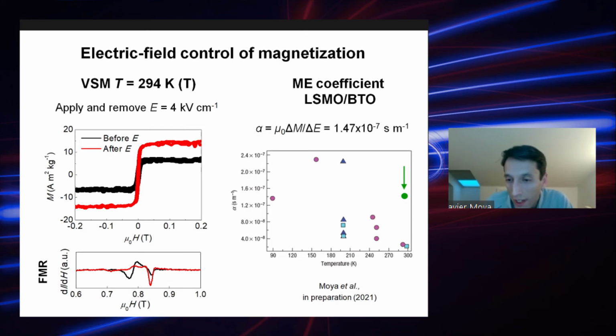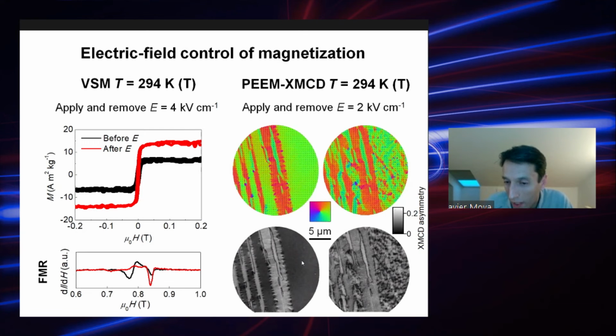And also interestingly, because you are in effect driving a magnetic transition, right? You're going from, let's say, paramagnetic to ferromagnetic. If you can control the microstructure of this material, you can also have very large caloric effects in the film, in this case driven with an electric field. So this will be an example of a multicaloric material.